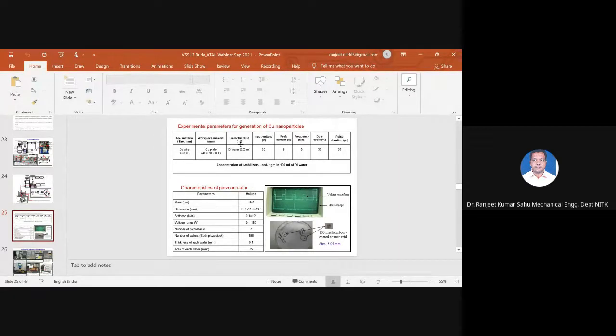We have taken the workpiece as a copper plate, and the copper wire is the tool material, and the various process parameters we set there. Then we have used a stabilizer at a concentration of 1 weight per volume percentage. Why we use a stabilizer, I will tell you in the forthcoming slide. This is the oscilloscope which is used to capture the voltage waveform. And when the debris come out from the workpiece, dispersing in the dielectric fluid, in our case the dielectric fluid is DI water, that is deionized water.